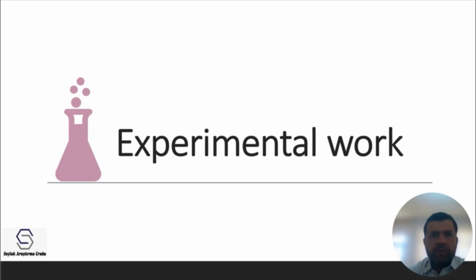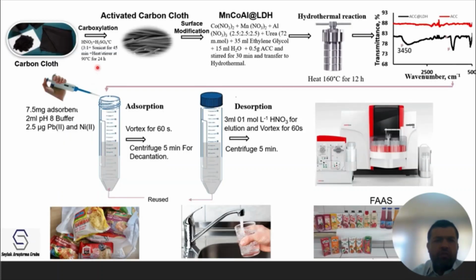Experimental work. So, the graphical presentation of my work. First, I synthesized a new material by the hydrothermal method, in which I took carbon cloth, cut it into small pieces, and activated them. After that, I prepared an LDH material and put them together into the hydrothermal reactor for 12 hours at 160 degrees centigrade. After characterization, the data suggested that the LDH nanocomposite material was successfully synthesized.